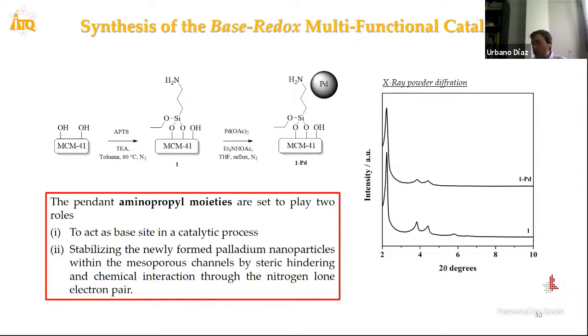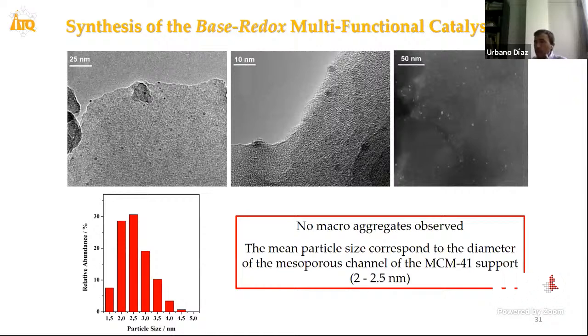The X-ray diffraction after the incorporation of these palladium nanoparticles confirms that the mesoporous character of these materials is preserved. From the magnification of the micrographs obtained by transmission electron microscopy, it's observed that no macroaggregate is present. And it's important to remark that the mean particle size corresponds to the diameter of the mesoporous channels of the MCM-41 used as support, confirming the confinement of the palladium redox species